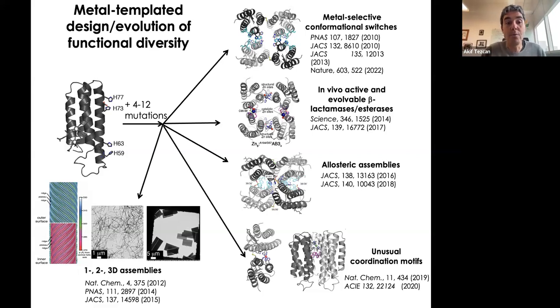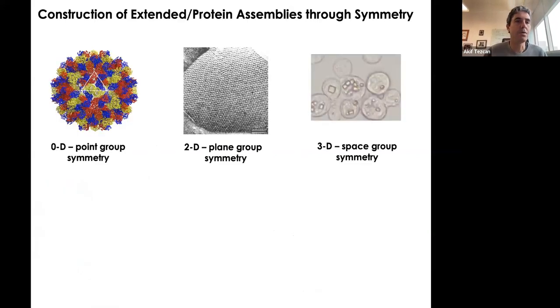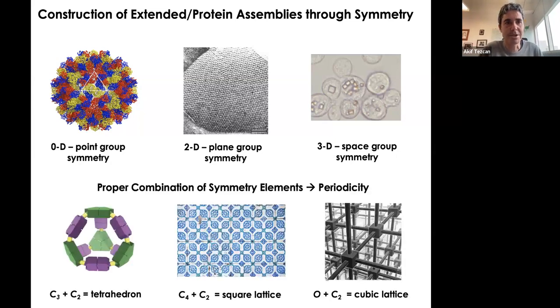So then we thought, hey, can we use these strategies to make any arbitrary extended architecture material with distinct dimensionalities? So can we make cages, for example, that have point group symmetries, or 2-dimensional crystals with plane group symmetries, or 3-dimensional frameworks with space group symmetries that we can actually do crystal diffraction, X-ray diffraction on?